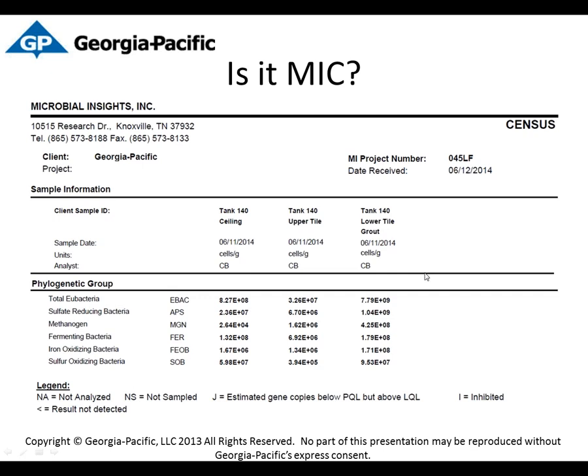So here are the bacteria reports we actually got from Microbial Insights. And these were some of the highest concentrations we found across the company to date. The sulfate-reducing bacteria were present in high concentrations, along with methanogens and fermenting bacteria. And like I said, this was another vessel that was only there for about 6 to 8 months. We started to see signs of corrosion on a vessel that you'd expect to last 20 years with no problems.